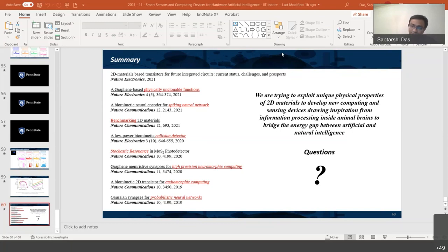Thank you, sir. Sir, is it also radiation tolerant? Yes, I think we have done a lot of work in the past. We have one paper on radiation resilience of this 2D material. And the fact is very obvious that these 2D materials are very, very thin, and something which is very thin is being seen by nothing, right? So even if you expose it to very large doses of radiation, we have done experiments with alpha particles, and we have shown that even the doses that you will experience in the different orbits of Earth are really minuscule changes to the device characteristics.